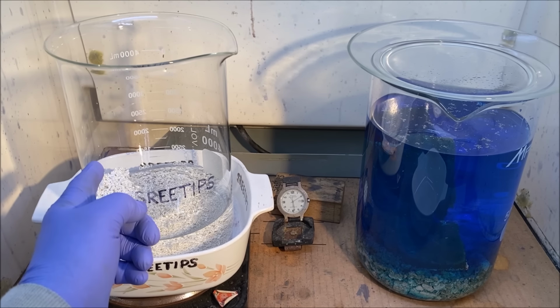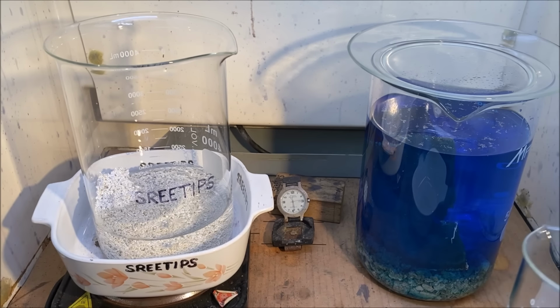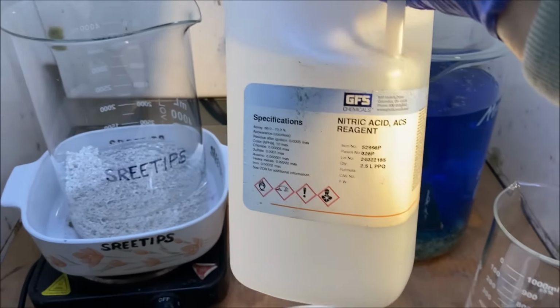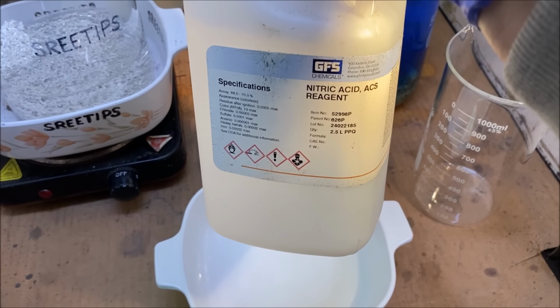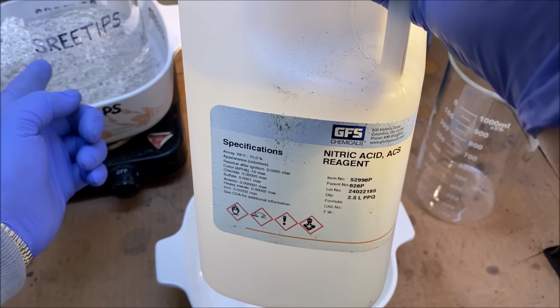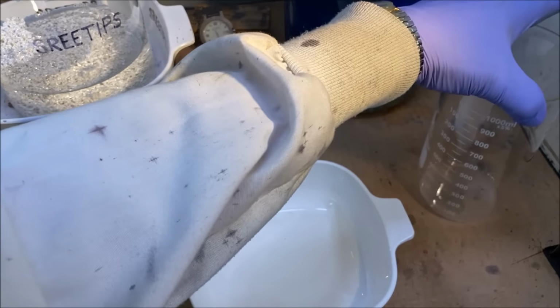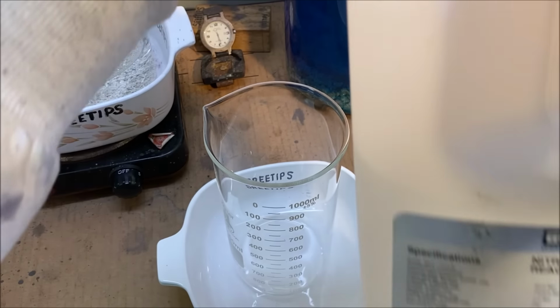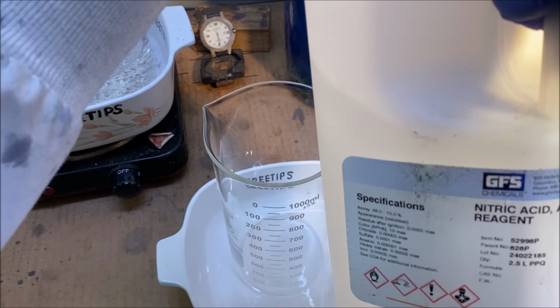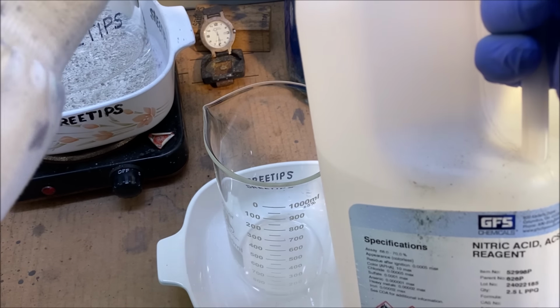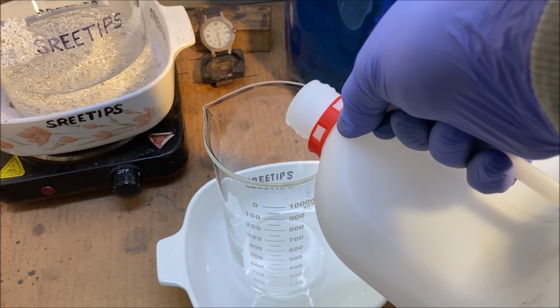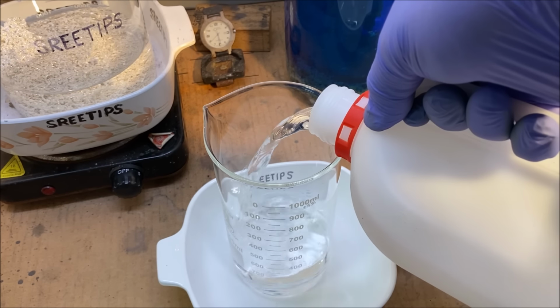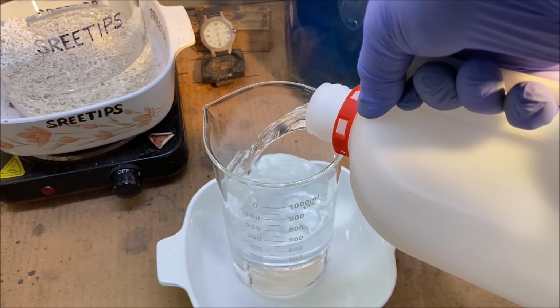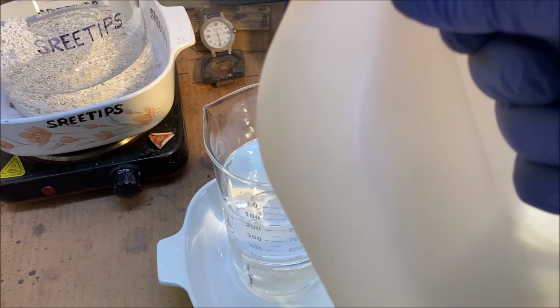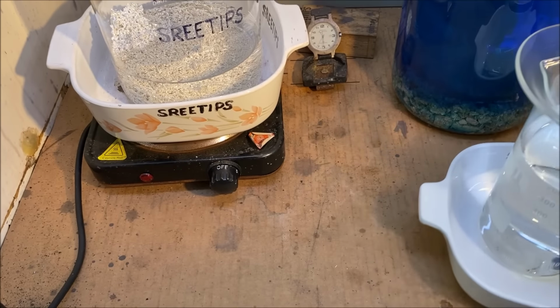It takes about 0.8 milliliters of nitric acid to dissolve 1 gram of pure silver. So I've got 1,000 grams in here that I want to dissolve. I'm going to measure out 800 milliliters of nitric acid, and we'll use this nitric acid to dissolve the pure silver in our beaker over here to make our electrolyte. Nitric acid.